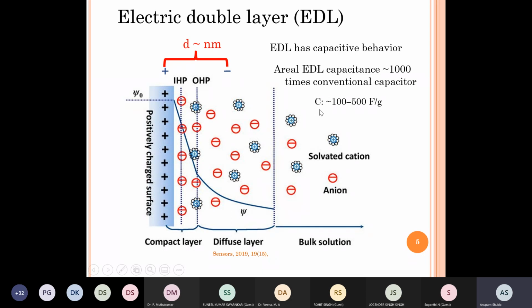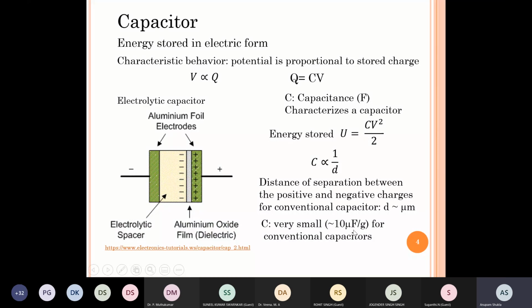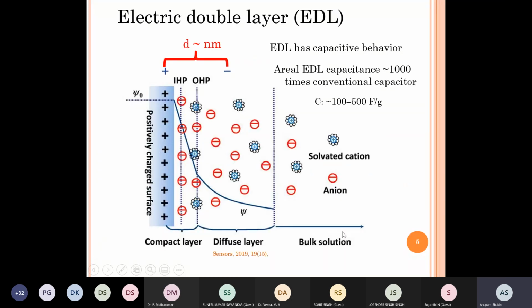And actually it turns out that for good materials, the capacitance can be as high as 100 to 500 farads per gram. Now compare this with what we put in the previous slide for the solid state capacitor, which is 10 microfarads per gram. Okay, so obviously this is not 100 times, not 1,000 times, but many more times than what we have shown in the previous slide. The additional order of magnitude improvement comes because the material which is used in the electrode for an electric double layer capacitor has lower density than what is used in the solid state device.